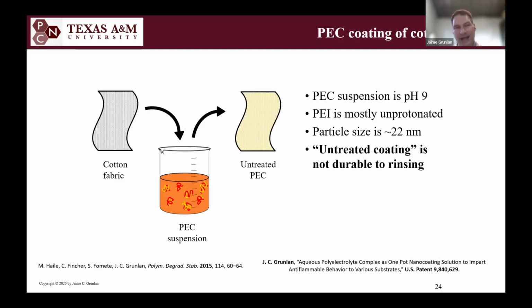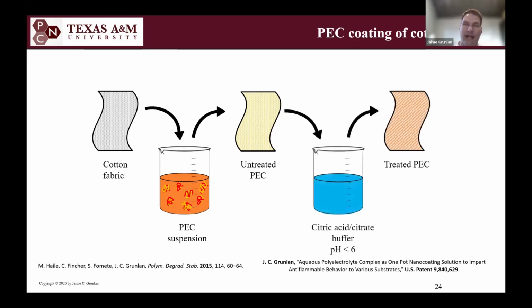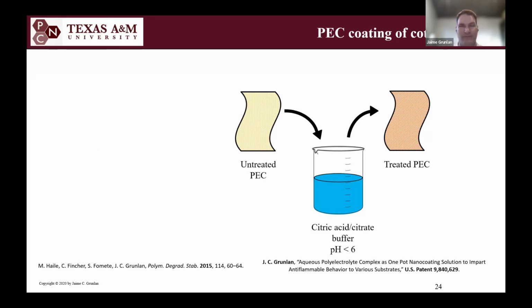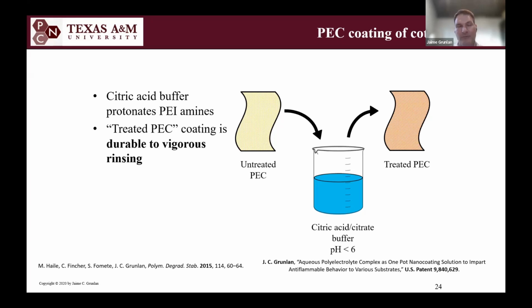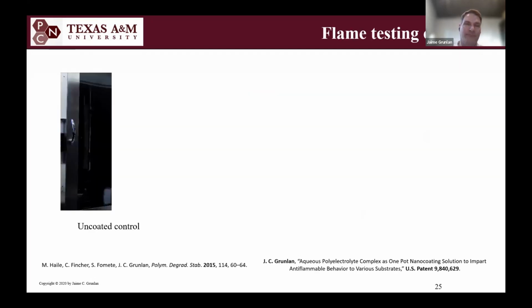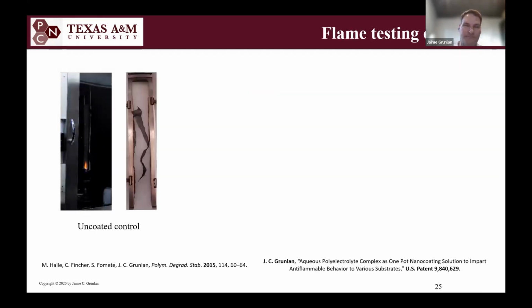And then I can take cotton fabric, I can dip it into that water-based solution with those 2 ingredients. And then if I then, as a second step, dip it into this citrate buffer that's at any pH below 6, it's going to effectively ionically cure those ingredients onto the surface of that cotton fabric. And then that's very stable to even very rigorous rinsing. It's not wash durable, but you could cross-link it as a second step if that was important.